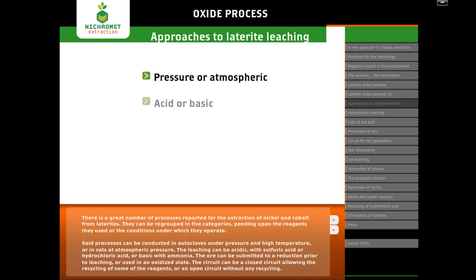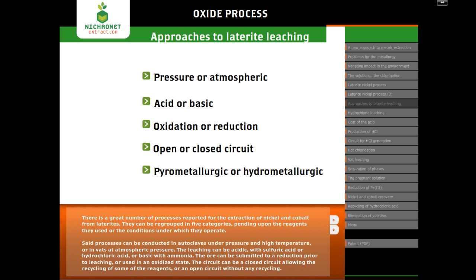There is a great number of processes reported for the extraction of nickel and cobalt from laterites. They can be regrouped in 5 categories, depending upon the reagents they used or the conditions under which they operate. Said processes can be conducted in autoclaves under pressure and high temperature, or in vats at atmospheric pressure. The leaching can be acidic with sulfuric acid or hydrochloric acid, or basic with ammonia. The ore can be submitted to a reduction prior to leaching, or used in an oxidized state. The circuit can be a closed circuit, allowing the recycling of some of the reagents, or an open circuit without any recycling. Finally, the process can rely on high-temperature steps, such as seen with the production of ferronickel or in solution at near ambient temperature.